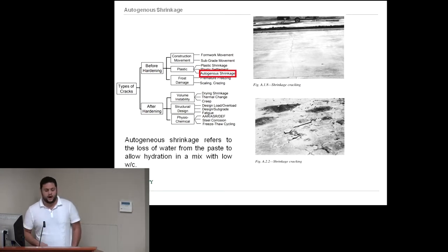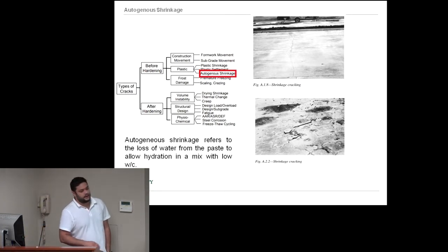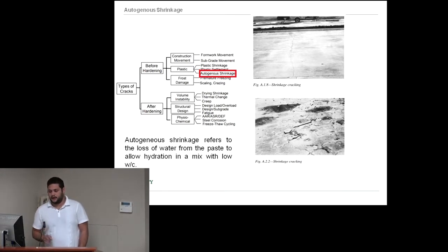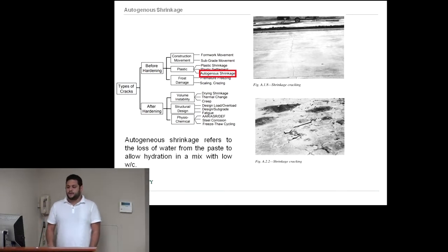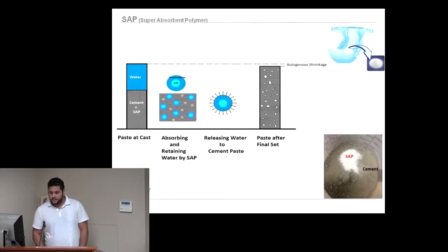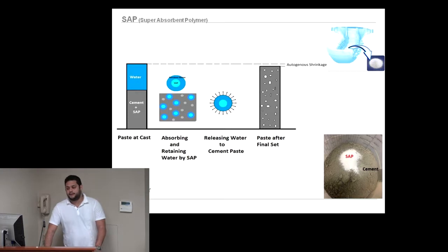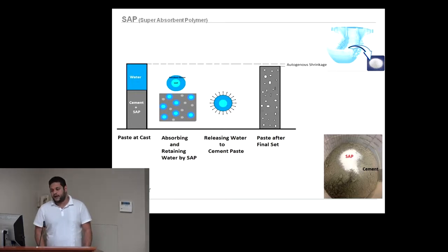Some of them happen before the hardening of the concrete, and some of them happen after the hardening of the concrete. So what I want to look at is the autogenous shrinkage of the concrete, which is the loss of water from the paste to allow hydration in mixes with a low water-to-cement ratio. Because we lose the water from the paste in the concrete, we will have cracks, but we have to do something to keep the water in the system.